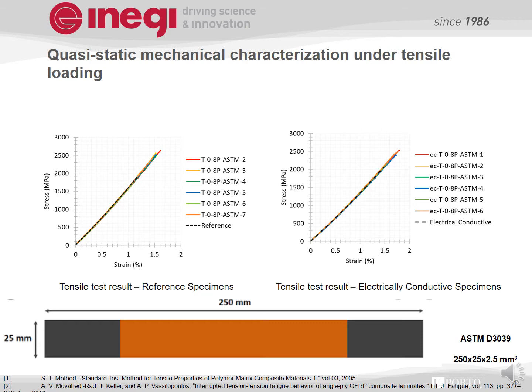The graph on the left-hand side shows the tensile test result of reference specimen, and the graph on the right-hand side shows the tensile test result of the electrically conductive specimens. Both the results show quite consistency in terms of the maximum force, maximum strain, and also the elastic modulus showed consistent values throughout the specimens.